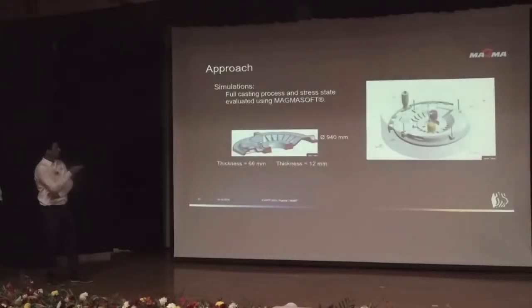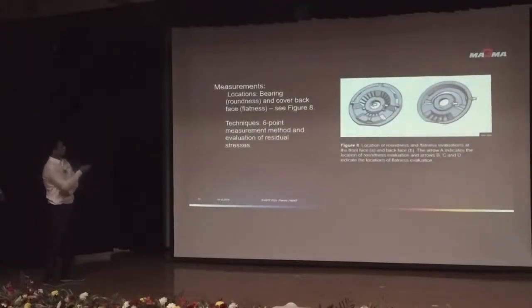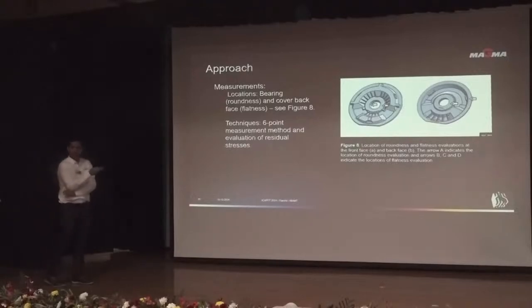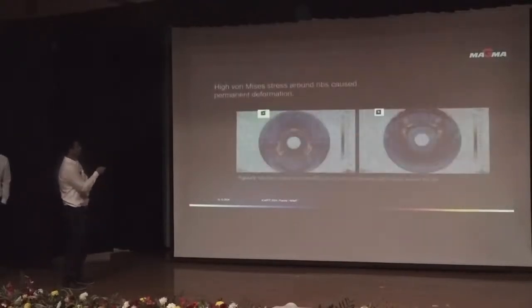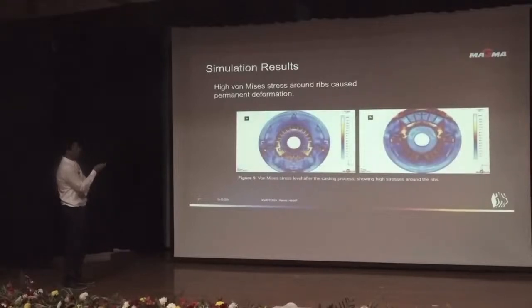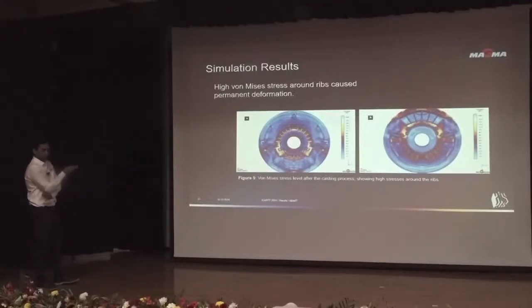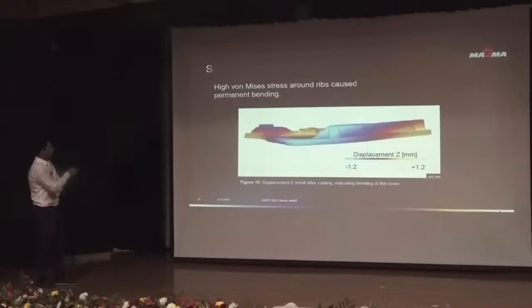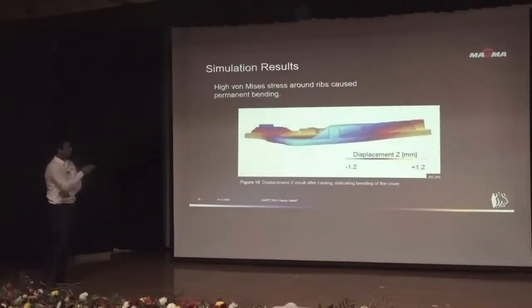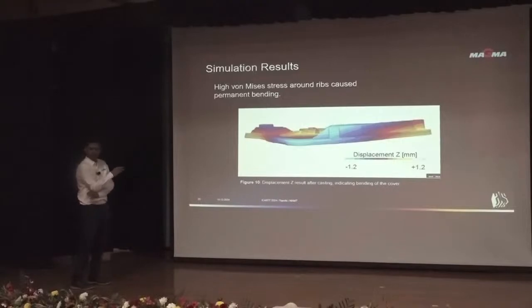So what simulations, these are the setups. And these are the measurements, the locations where we are going to measure the roundness. There we used a 6-point measurement technique. These are the von Mises stress results, which are causing deformation around the inner sections and the outer layers of the casting. And this is a section view where high von Mises stresses around the ribs were causing a bending issue.